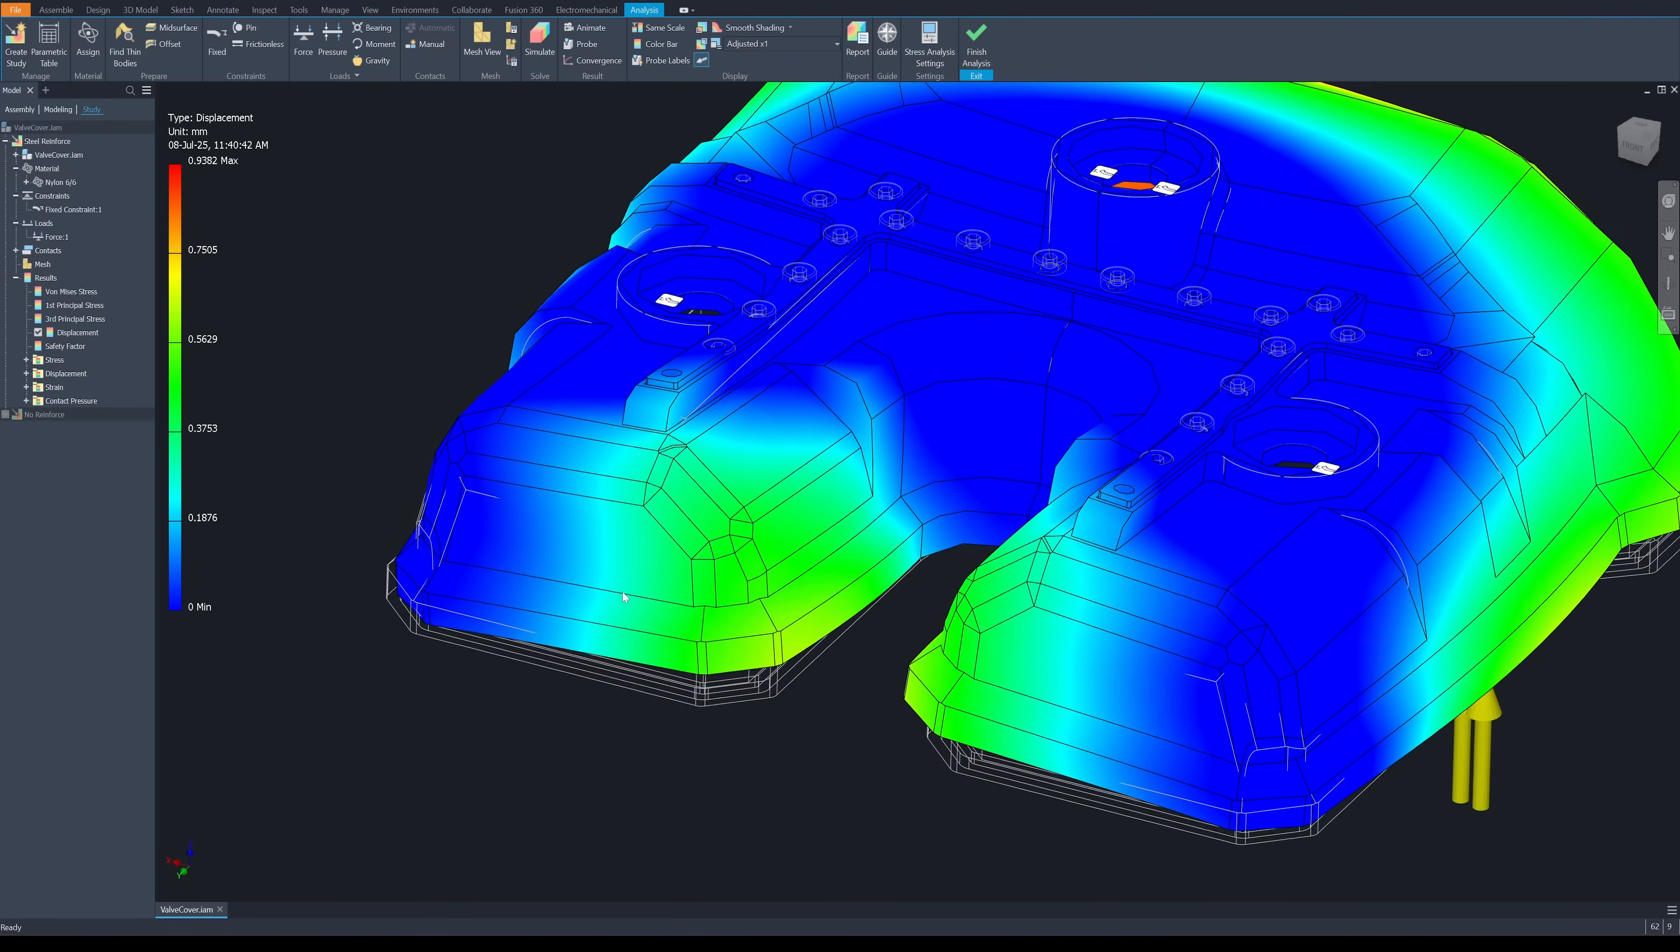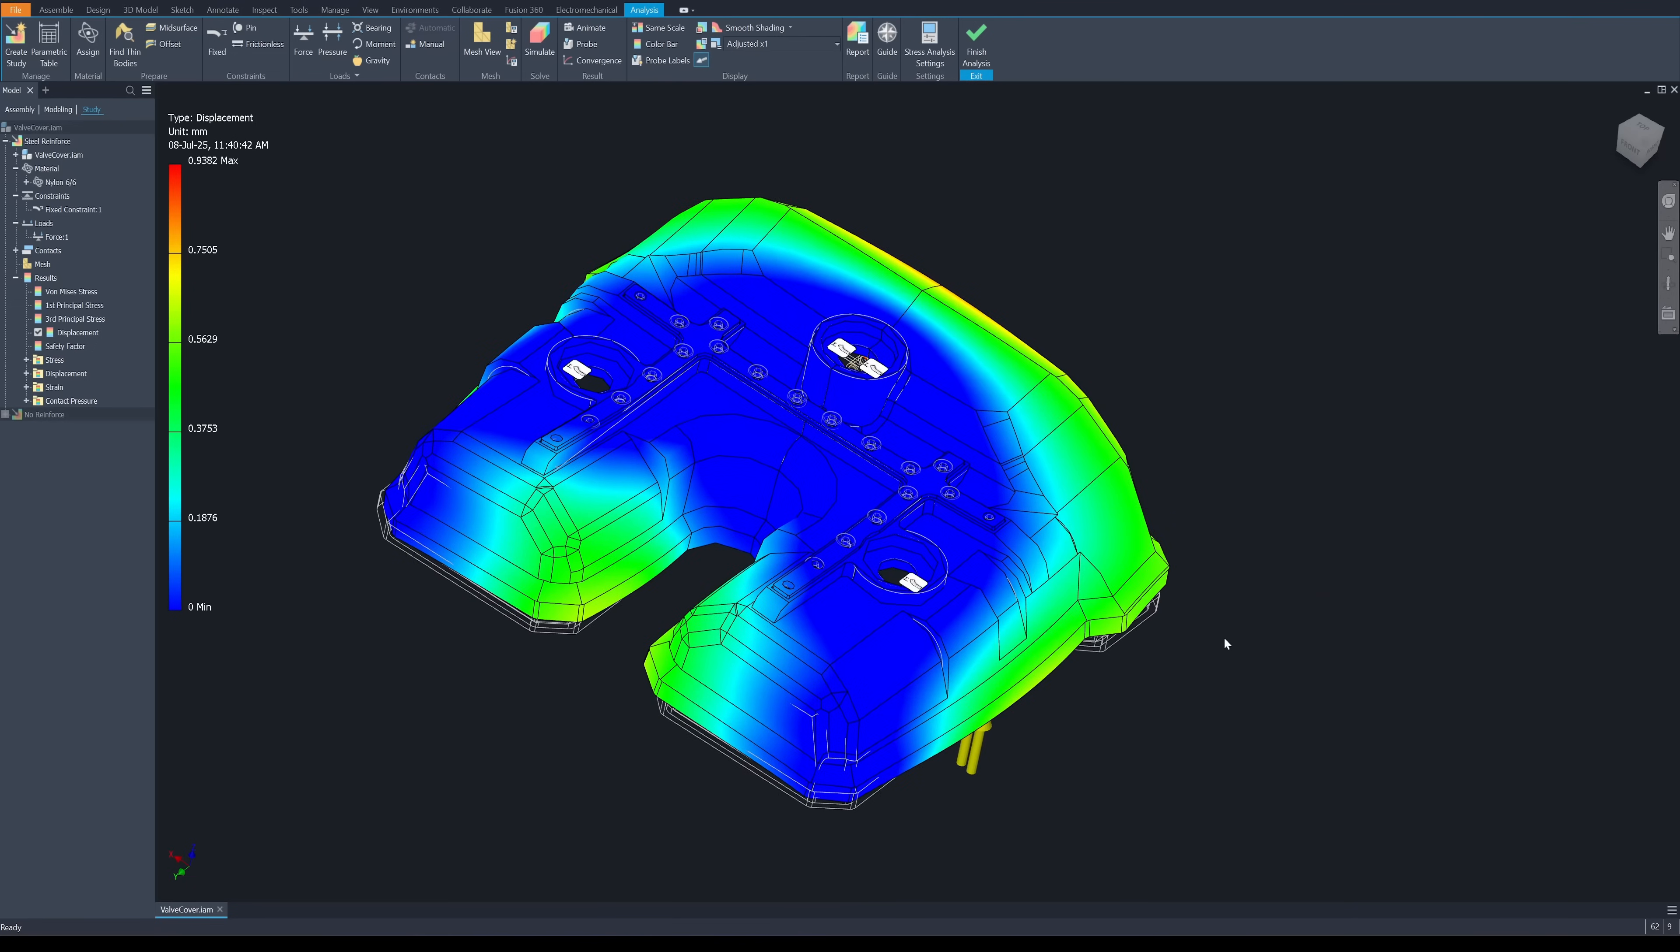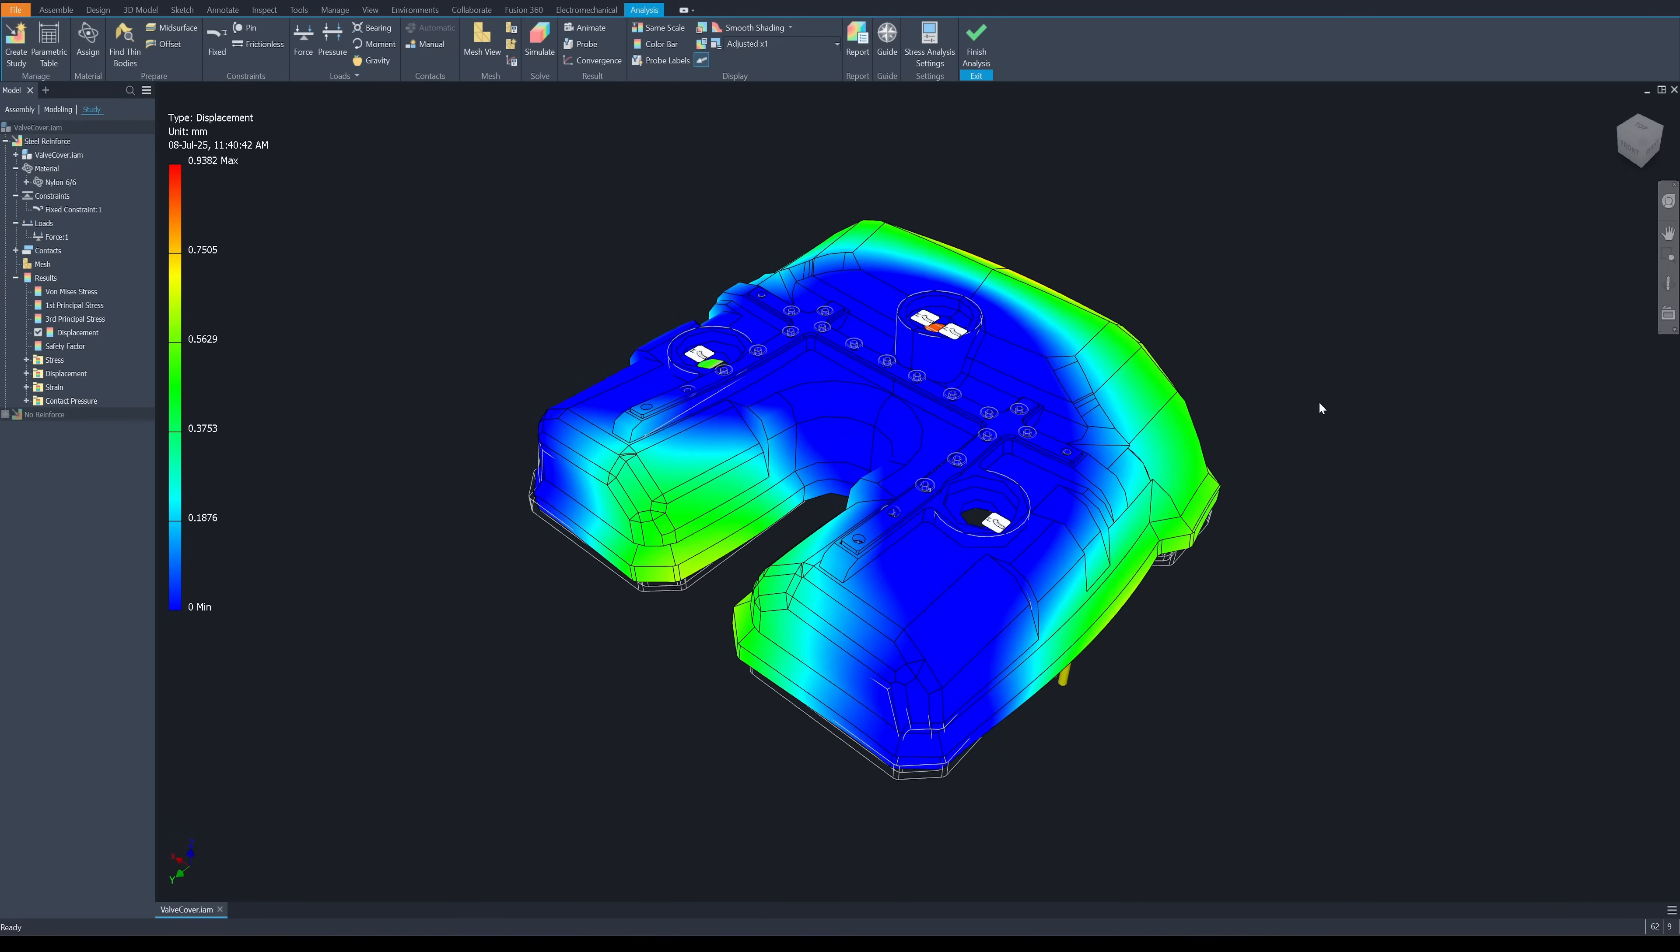And the displacement value, see here, it will go down to at this point 0.5 mm. And in the back, it's 0.9 mm. So this part will bulge out for about 1 mm. So if I use nylon with carbon fiber, the deformation will be less than this. But with the help of the stainless steel plate, it can reduce the deflection by half. I think this would be the best way to control the deformation on 3D printed plastic parts.